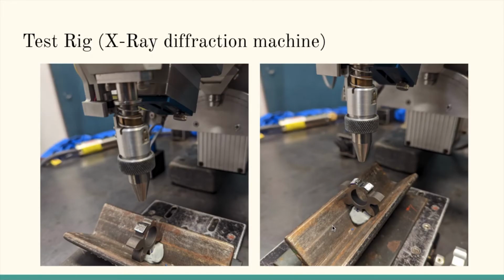See one of our samples set up for X-ray diffraction at TEC, with measurements being taken parallel to the root and perpendicular to the root. Measurements were taken at the surface and at a depth of about 50 microns for a total of 4 measurements for each sample. As you can see, our samples had to be sectioned in order to properly get X-rays into the root of the gear.